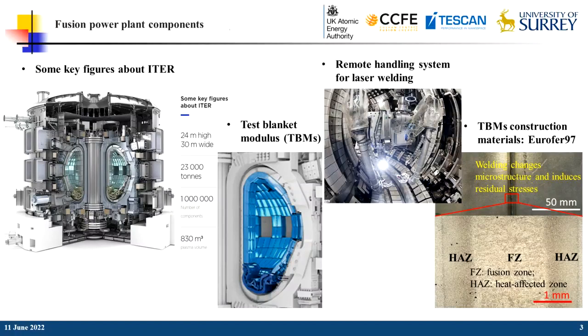Remote laser welding is one of the most promising techniques for assembly and maintenance of the in-vessel structures. This technique gives less distortion and enables full penetration of single-pass welds in thick sections. It has low heat input, leading to a narrow heat affected zone. However, this welding process still induces significant residual stresses of up to approximately 800 MPa inside welded Eurofer97, and changes the microstructure and the mechanical properties.